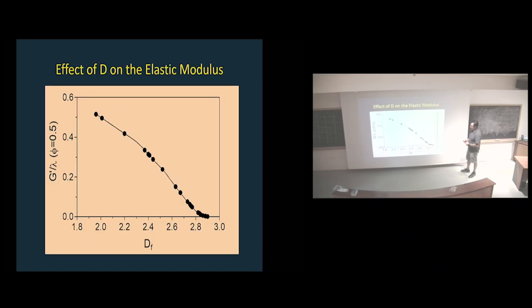And you get nice behavior from many, many different systems in which you just normalize your G prime by the pre-exponential factor of the power law, and you get this nice behavior that is related to the apparent fractal dimension of the system. And look at the range that we get in natural systems. Yes, we get stuff around 2, which people can talk about DLAs and RLAs or cluster aggregation, but we also see these very densified things. Forgive me if I say something wrong, but I mean a DLA in 3 dimensions is around 2.5.